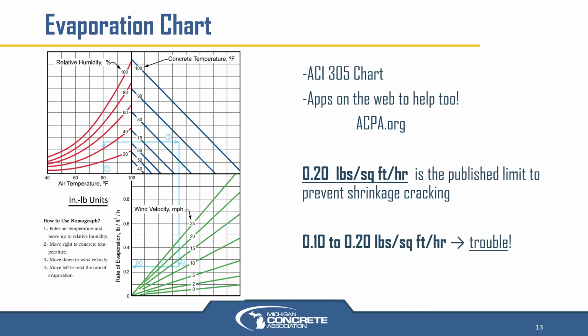They have an app on their website that you just plug in the air temperature, relative humidity, concrete temperature, and wind speed. And it tells you what the evaporation rate is, in pounds of water evaporating per square foot per hour, technically from the concrete slab, but it was based on data from a pond. But at any rate, it's still what we use to this day. We know that 0.2 is always the critical number for shrinkage cracking. However, I've found in my experience, 0.1 is actually the number that we really need to pay attention to for curing compound. Once you get down to zero evaporation, you can get away with, quote unquote, not curing your concrete, because it means there's no wind and it's 99% humidity and there's no evaporation happening from the surface.